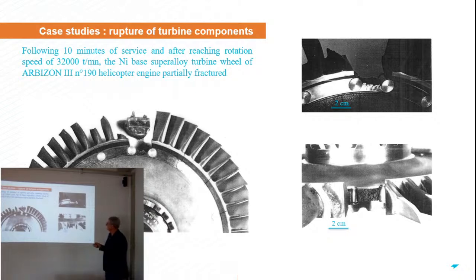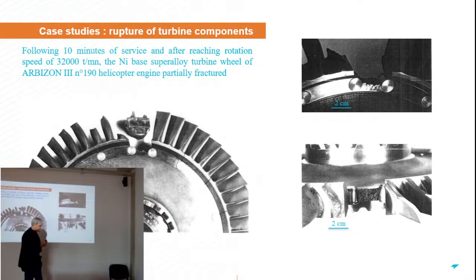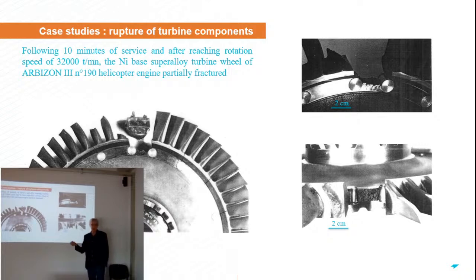So you can see here a very rapid failure, which means that probably there was not enough time for fatigue of the material. And you can see here, close to the fracture, some plastic deformation. And you can see here on the fracture surface itself that you don't discriminate two zones. So probably no fatigue here, only an instantaneous fracture of the material occurring very, very quickly. So this is what we call a ductile fracture, because you can find some plastic deformation, and an instantaneous fracture, not related to any fatigue of the material.